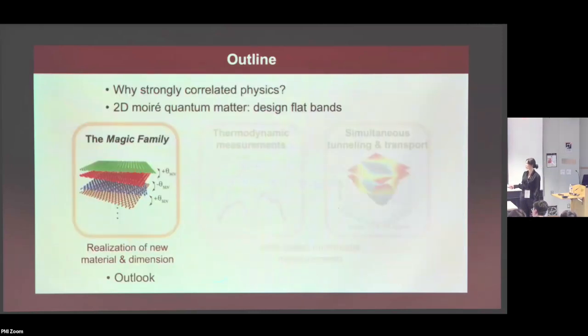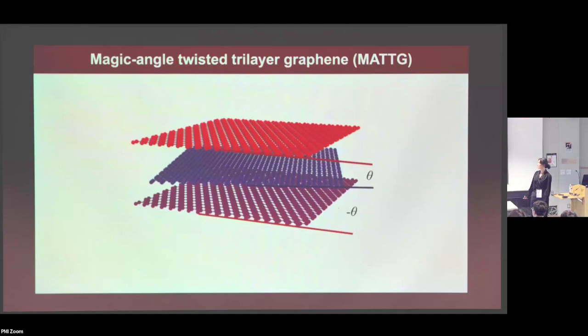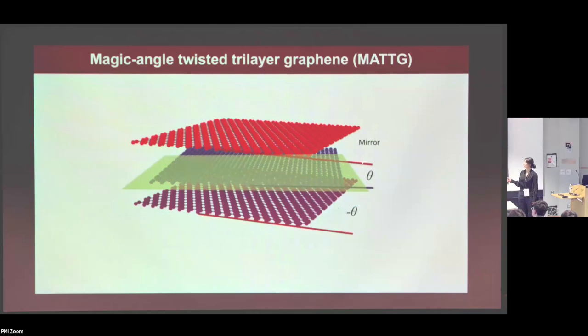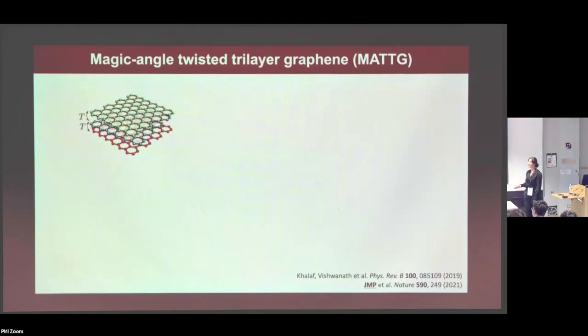So that was the first part of the talk, where we made this so-called magic family. The first system we looked at is twisted trilayer graphene, where you have three layers of graphene and the adjacent layers are twisted by theta and minus theta, such that the top and bottom layers are aligned and the middle layer is at a relative twist angle. This system has an extra symmetry, a mirror symmetry, that was not present in twisted bilayer graphene. How do we understand this three-layer twisted structure? In general, with multiple twisted layers it's much harder to calculate a band structure, because you might have different Moiré periodicities at the different interfaces, and might also form super Moiré and so on.